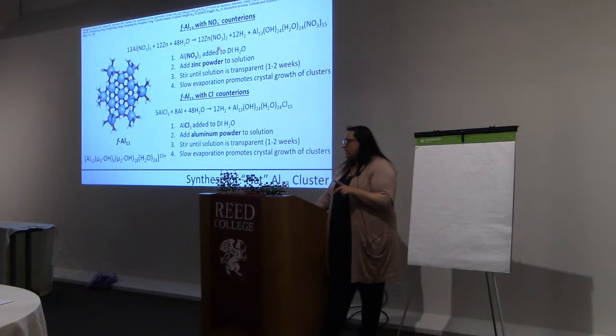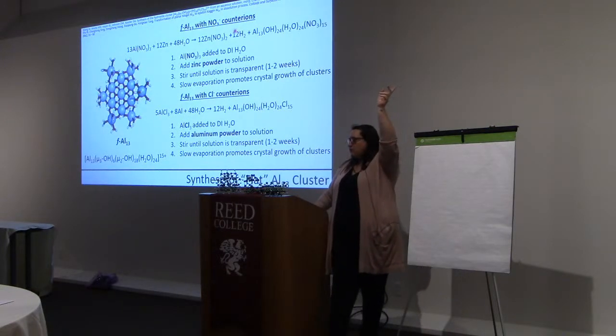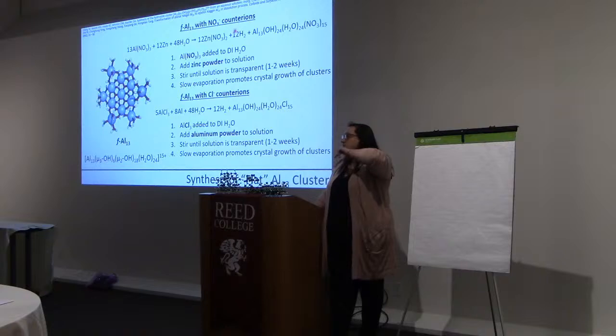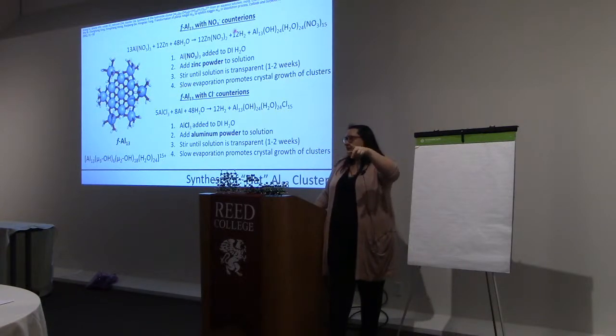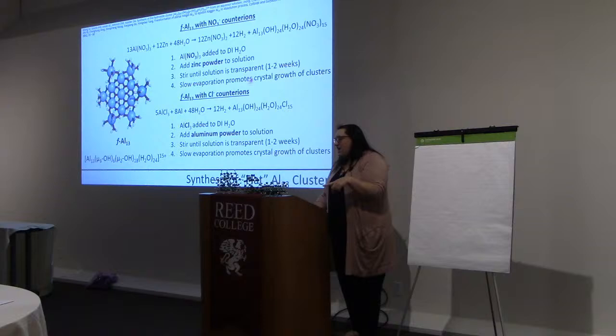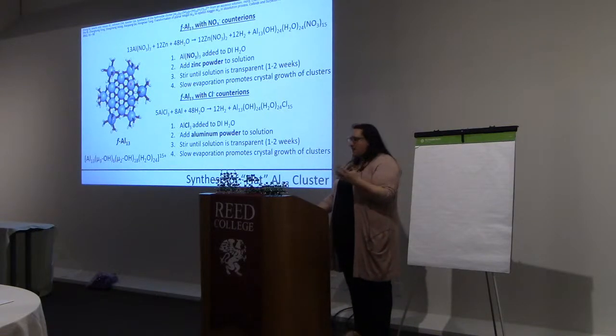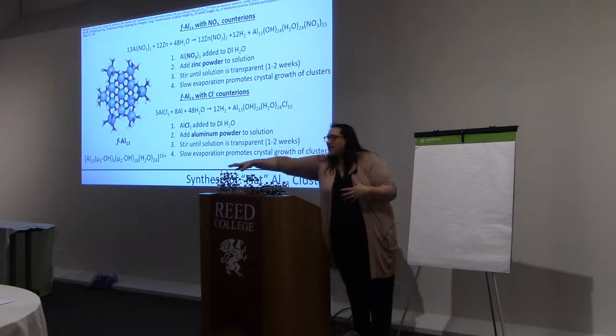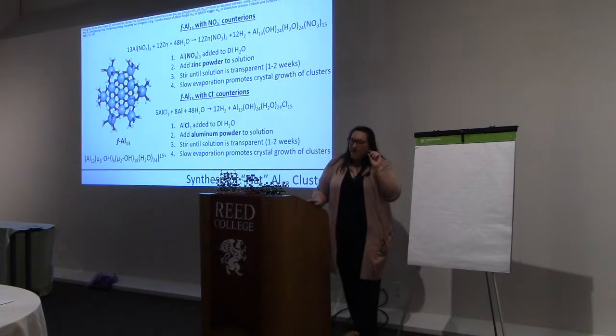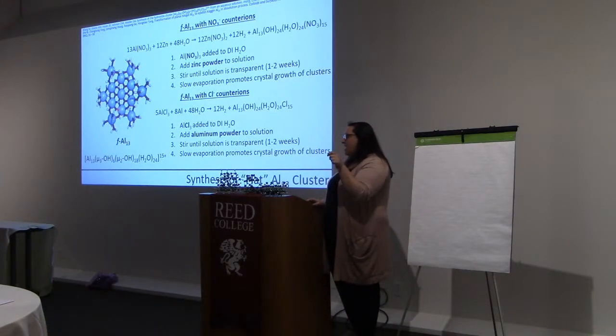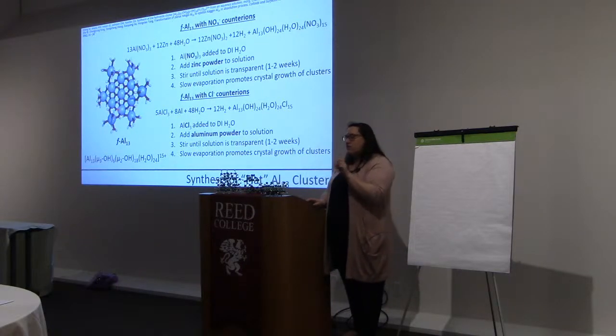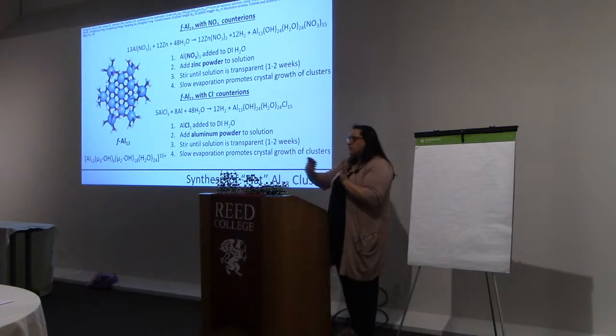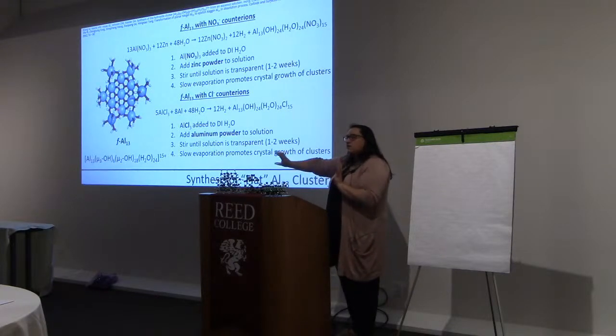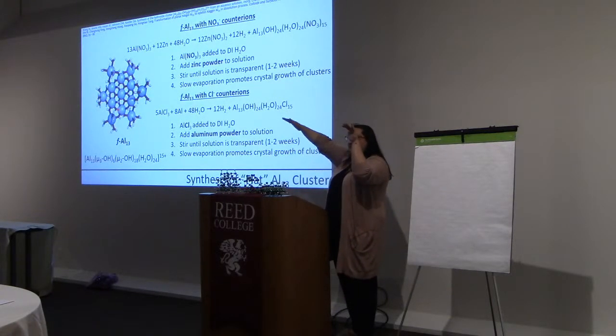So we have a redox reaction here that's creating hydrogen gas bubbling out of the solution, which is making our pH go up because we're losing hydrogen. So we're building hydroxide bridges and forming these clusters. The reason that we hypothesize that this cluster forms instead of the Keggin is because, instead of adding base and having little micro environments that are very basic, where a tetrahedral aluminum would form, we are very slowly raising the pH through this redox reaction, and so we're not getting any micro environments that are very basic, and no tetrahedral species ever form.